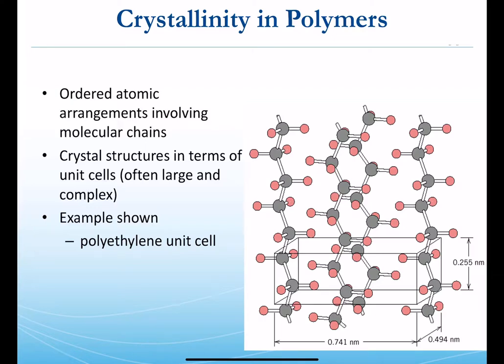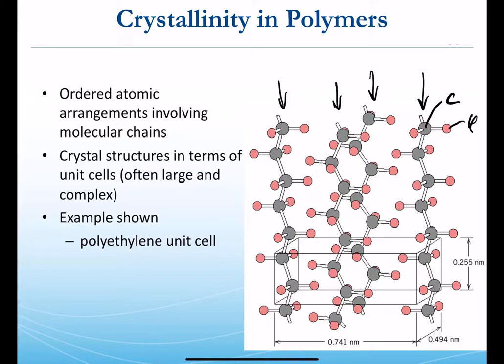Some polymers, if they're regular in structure, can give us an additional packed arrangement that is very regular. Here is polyethylene, where you can see the carbon atoms in gray and hydrogen atoms in pink. You can see from this visual that there's a unique and predictable pattern for these neighboring chains that are packed in a perfect arrangement where a mathematical process could predict where the next carbon or hydrogen atom is, ultimately settling on something called a unit cell.